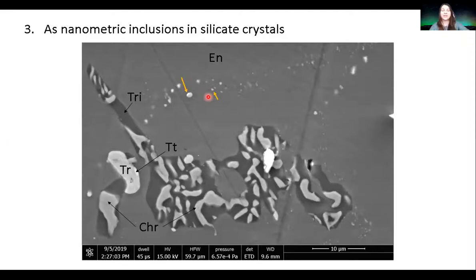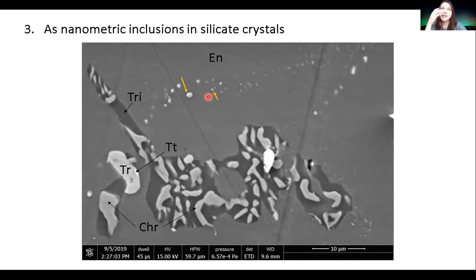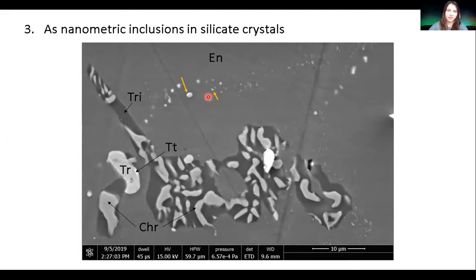There is a very, very tiny — about 70 nanometer — high-nickel grain. I tried to do EBSD on this and ran into a lot of resolution issues; EBSD at least the way I did it didn't really cope with that level of small size. So I couldn't establish that this was tetrataenite. Given that tetrataenite was present in the rest of the sample, it's a fair assumption that the whole sample didn't get reheated above the ordering temperature long enough for tetrataenite to revert to taenite — but it still couldn't be established confidently.